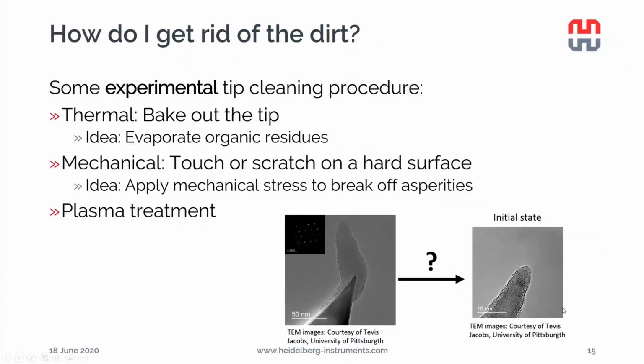Some of you might ask, if you have the initial state and we have this contamination, this looks quite fragile. Can we go back by cleaning the tip somehow? And indeed, we had some good success with some experimental procedures to clean the tip. One thing is basically to turn on the heater in air, raise the tip temperature to a couple of 100 degrees, and hope that this contamination will simply evaporate.